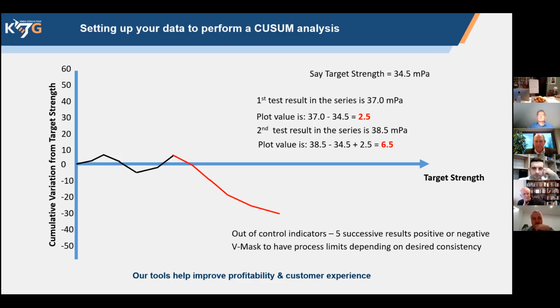Or there's a thing called a V-mask, which looks at different process levels for desired consistency, and the amount of consistency determines the width of the V-mask. You can put the V-mask over the lead point here, and in this case it's very, very tight, but wherever the line crosses would tell you that there is an out of control situation. As we can see here, the first line crosses here, and also corresponds with 5 poorer than desirable results in a row.